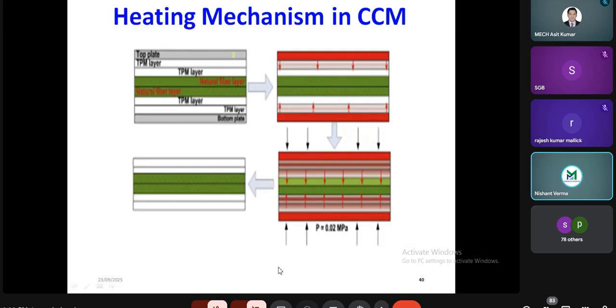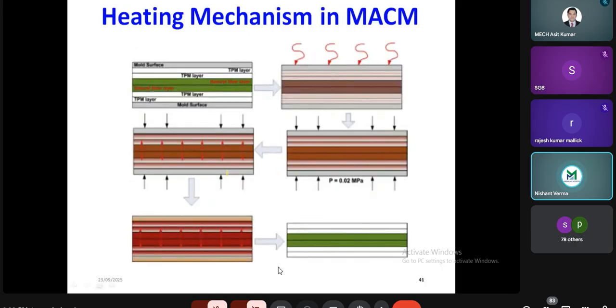These are the matrix layer, these are the fiber layer, and the heat transfer takes place from the surface to the core. This surface is connected with the bottom and top plate of the conventional compression molding, and it transfers its heat from the matrix to fiber, and again the sandwich and fabrication takes place. While in case of microwave assisted compression molding, the heat interacts with the fiber, and after interaction it transfers its heat to the matrix material. In this way the fusion takes place.